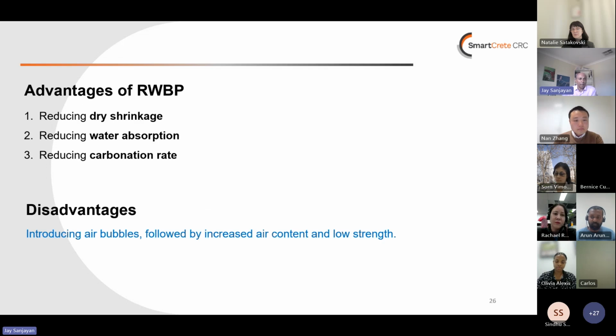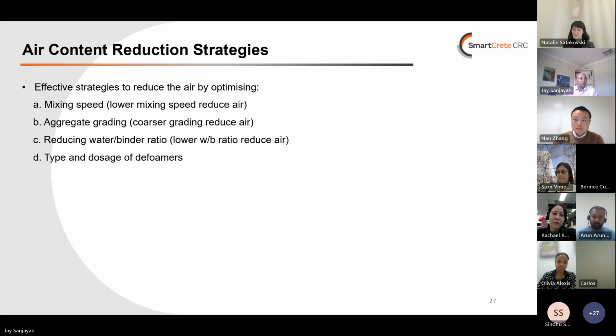So the advantages are drying shrinkage, water absorption, and carbonation rate. The main issue that we need to address is the strength reduction and the air content. We have done some other research to look at the mixing speed. If you have a low mixing speed, we have low air. Also, finer aggregate grading increases the air, so we need to make it coarser grading. Water binder ratio decrease, the air decrease.